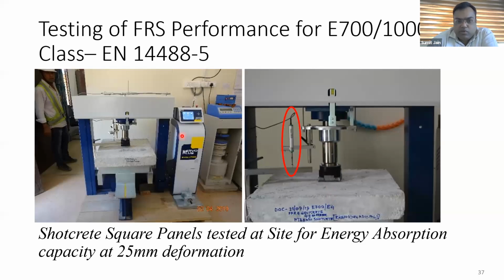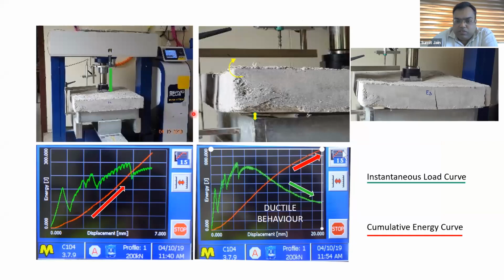Here you can see there is a display control. All the graphs and everything are instantaneously displayed on the monitor, and after the test is over, you can get a printout of what you have done. These are some of the images we have tested. The first image shows the load which is gradually applied on the panel. When the load is applied, this is the instantaneous load curve, and this is the cumulative energy curve. Two curves are plotted simultaneously.